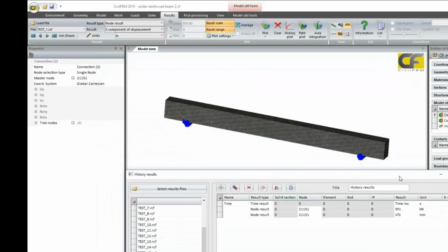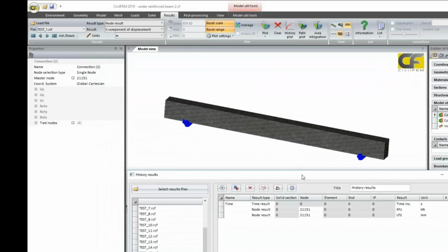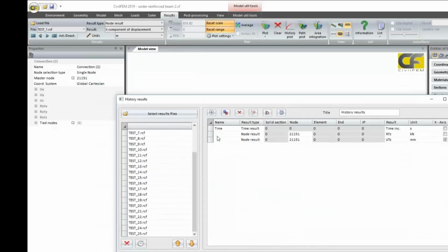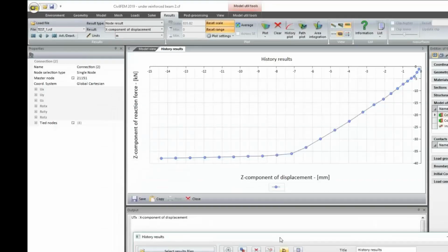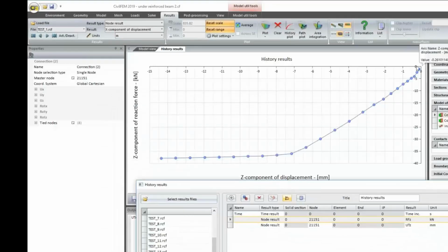And if we plot, in one of these points, vertical displacement versus the load, we get this type of curve. In this case we have a ductile behavior. In the first step here we have a modification, which could mean cracking starts, but mainly elastic behavior. And then we have a horizontal branch, and the maximum load that we can apply is between 35 and 40 kilonewtons.